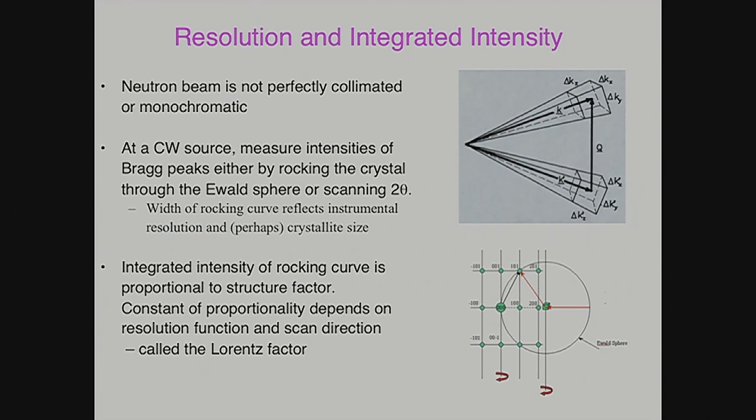On the other hand, if you're trying to do backscattering, you're trying to measure very accurately the change in energy of the neutron. In that case, it's absolutely pointless to try to do it if you don't know this length, because you don't know the energy of the incident neutron well enough to measure the energy change. So in that case, you tend to make this dimension very large, and this dimension, the longitudinal dimension, very well defined. So you'll find that all of the instruments have these sorts of compromises in them. And that's the reason why there are so many different types of instruments, because you make different compromises in order to measure different types of science.